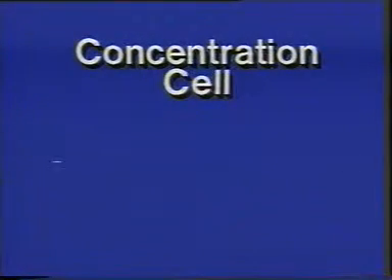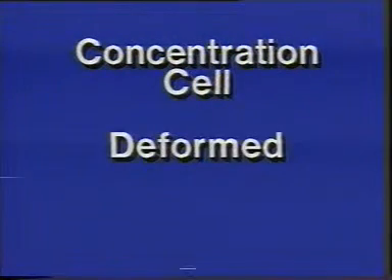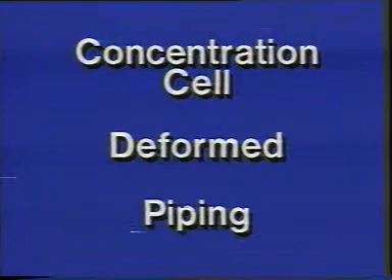Wire mesh will corrode first at points where wires cross, for two reasons. First, iron oxide is cathodic to iron. Secondly, the oxygen in the water cannot reach the crossover points well. This is known as a concentration cell. Plastically deformed material becomes anodic to metal that is not deformed. An example would be serial numbers stamped in metal. To prevent corrosion in underground piping, more active metal anodes are electrically connected to the pipes so that they corrode rather than the pipes.